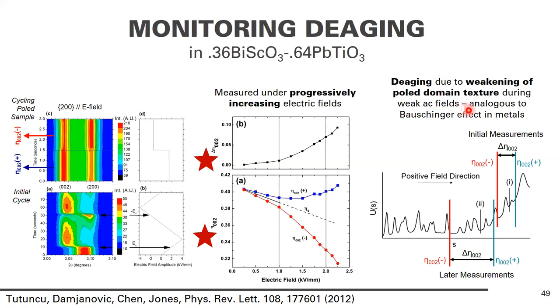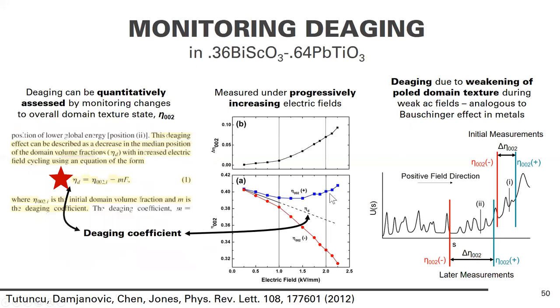And then we also said that this is analogous to the Bauschinger effect in metals, which was a nice parallel between metals and ceramics. And just for inspiration for the grad students, when we first submitted this to the journal for review, the reviewers came back and said this really isn't Physical Review Letter quality because it doesn't have enough math. So what we did in the revision process was we fit this eta D, this de-aging curve, to a line, and we created this equation, and we called this a de-aging coefficient. And that satisfied the reviewers.